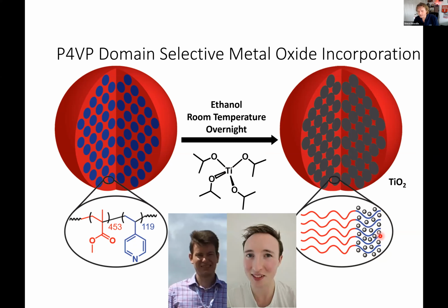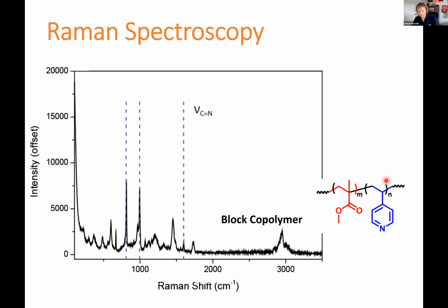When this happens, the titania would like to stick into those areas. What we can then do is heat it up and remove all of the polymer and just leave behind the titania. The polymer should have acted as a template.